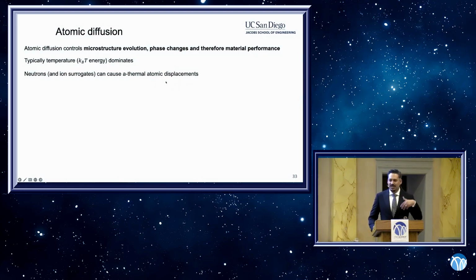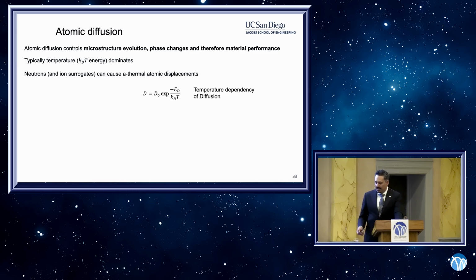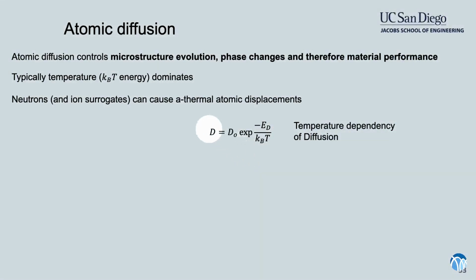So the atomic displacements that are not caused by temperature, but are caused by the neutrons impacting on the material itself. If we want to write an equation here about this, D is the diffusivity, which controls how fast the atoms can move in the solid. And what you see here is an exponent, and we see that the diffusivity increases exponentially with temperature. So the hotter you get, you're dealing with an exponential response to how fast those atoms are moving.